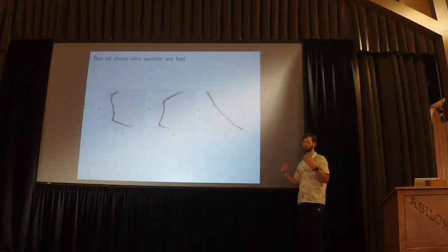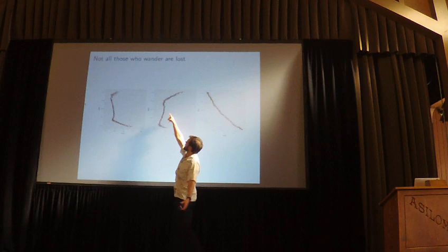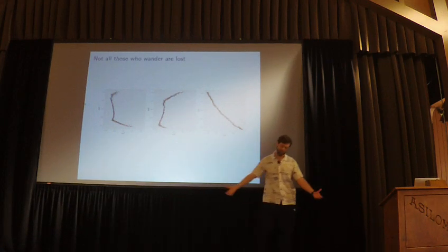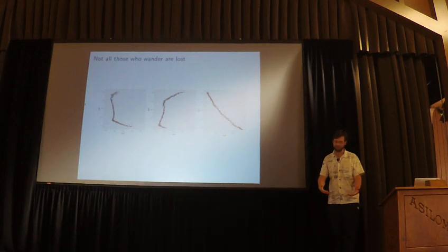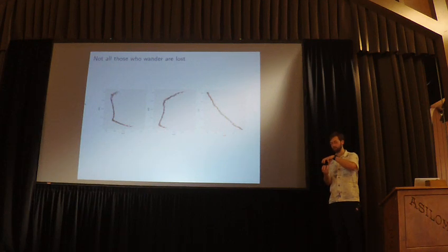It's not that the misorientation doesn't matter. It's that this non-identifiability in our model exists on some sort of ridge. And so what this is telling us is that there's something really interesting about the sample that we're working with that we didn't think about before. I think the running hypothesis is that instead of a single crystal material, we're actually working with a material that, think of it like columns of material glued together and then cut out into a square.